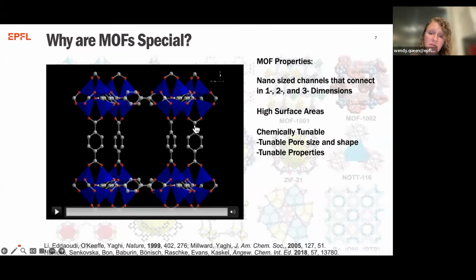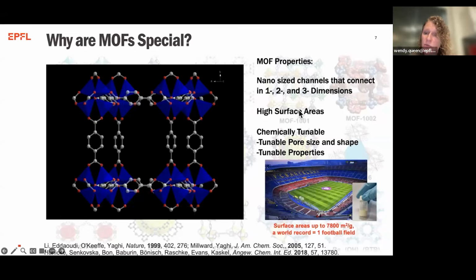As you know, the walls of these materials literally are atoms thick, and this gives rise to world record surface areas. So in a single gram of material, you can have surface areas as high as 7,800 square meters. Also, pore volumes above 5 cc's per gram, for instance. This allows us to effectively put a lot of guest species inside.